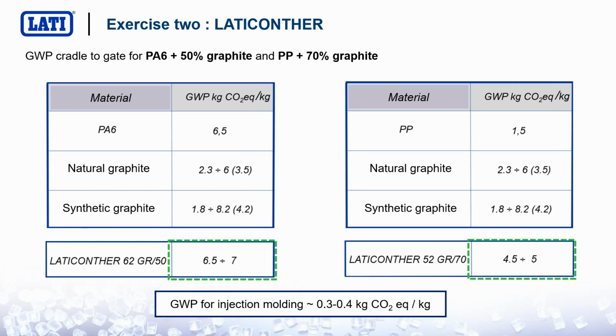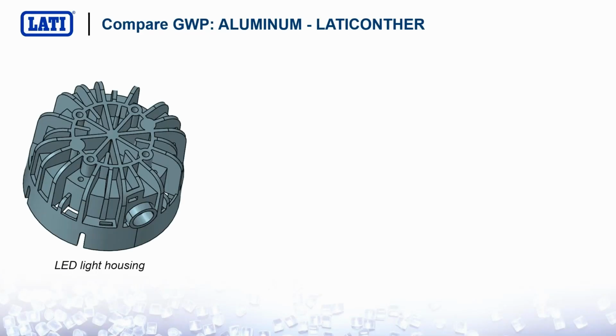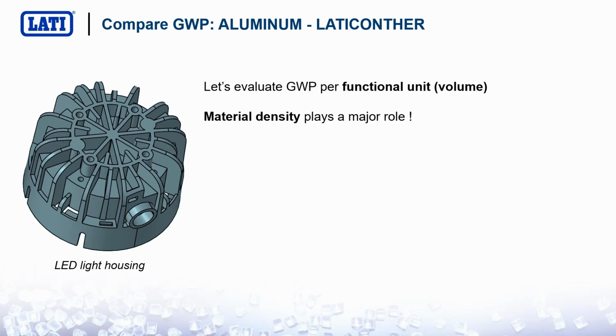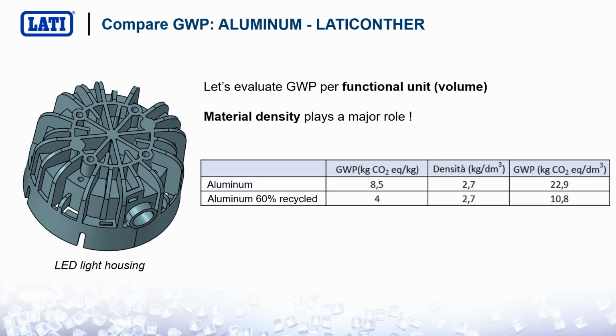Now, if we look at this number and remember the 4 of the die cast, we may ask, okay, so what's the point? The point is that you have to consider the density of these materials. So for a proper part, for an application, as the LED light seat you see here, you have to evaluate the global warming potential of a functional unit. So you have to evaluate the global warming potential per volume, not per kg. So that's exactly where density difference kicks in.